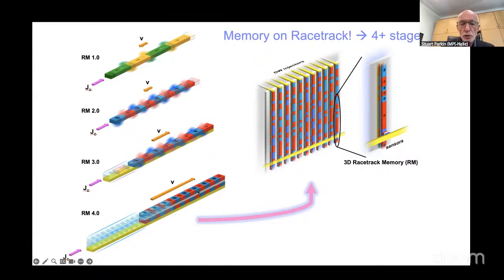So in this cartoon, if you look closely, you can see wherever we have a red region in the upper racetrack, it's blue in the lower racetrack. It means the magnetizations are pointing in opposite directions. And so by design, we could design these two upper and lower racetracks to have opposite and equal magnetization. So now there's no net magnetic flux. We've eliminated all the dipole fields.